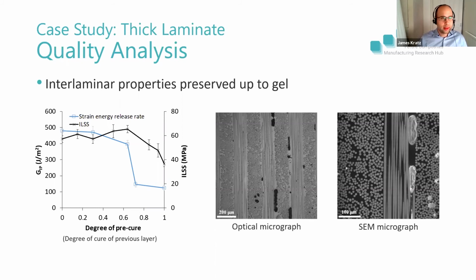So with layer by layer, we have intensified the process. We need to keep an eye on whether or not we're actually changing the microstructure of the composite and whether those properties are equivalent to a baseline. But overall, the quality looks really good. The porosity is fairly low, and the interlaminar properties are there.